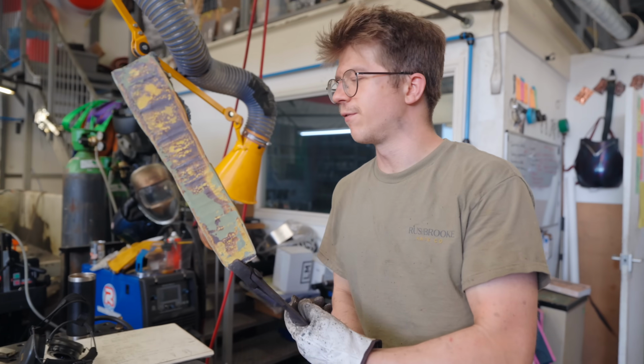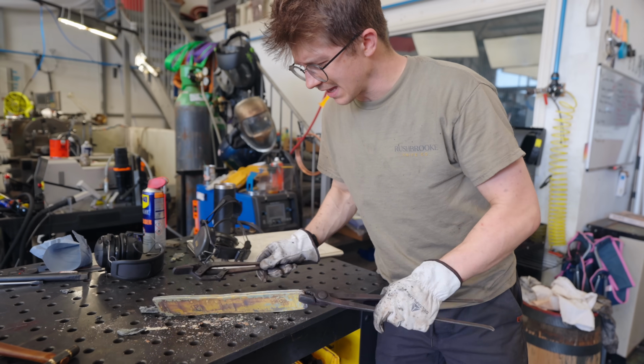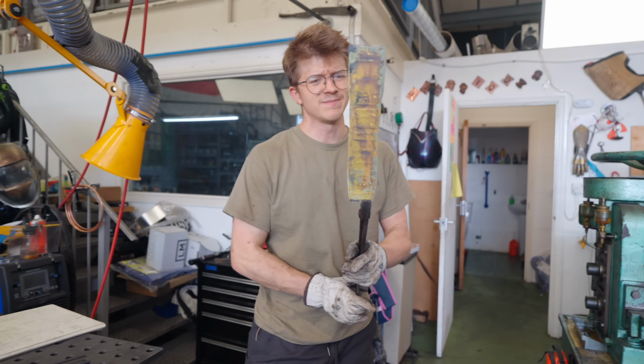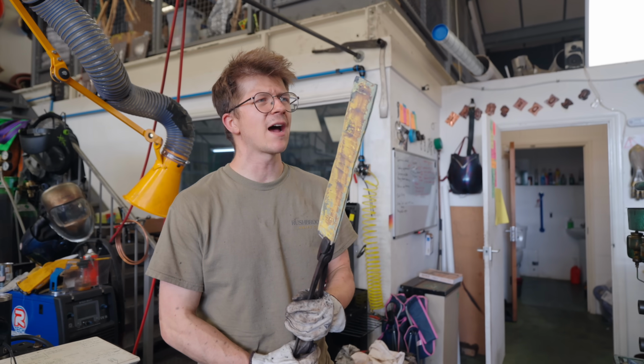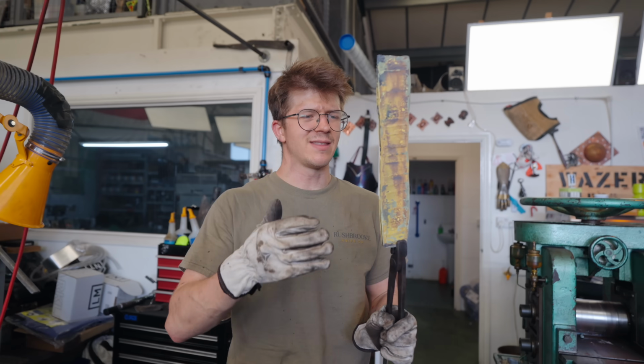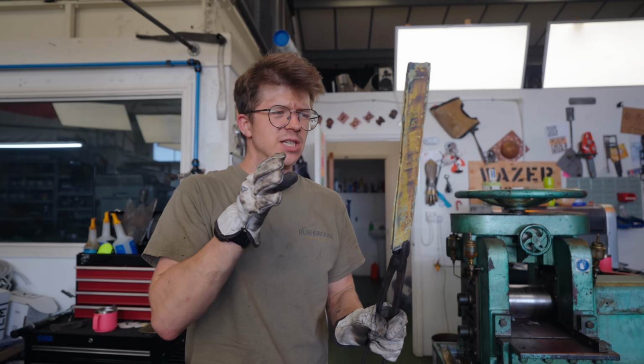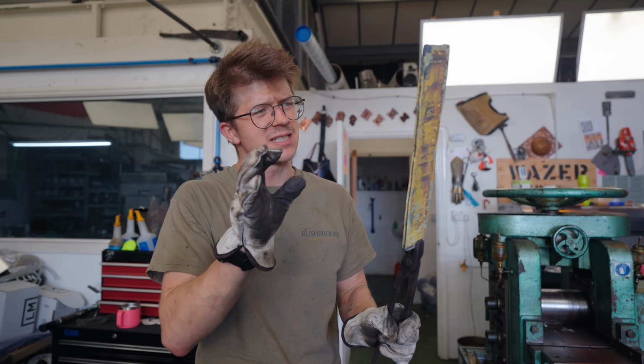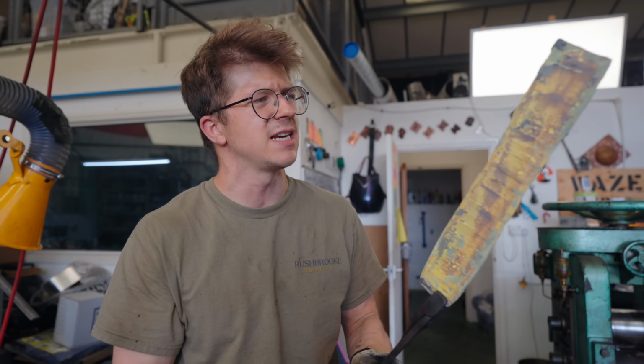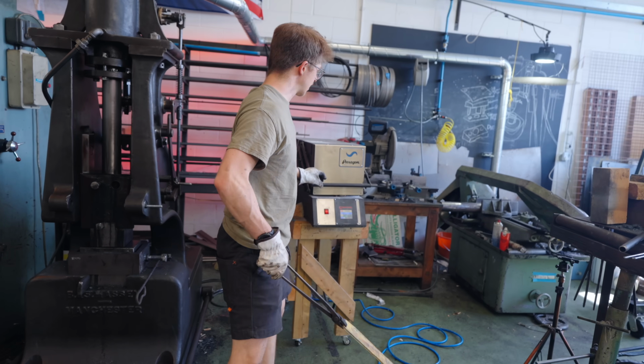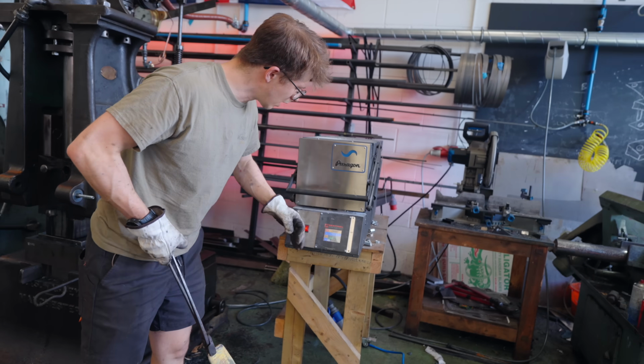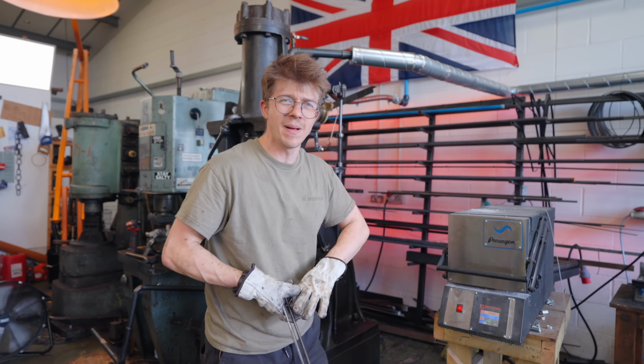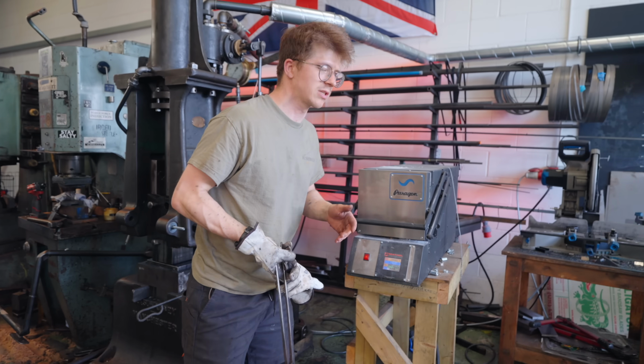That, unfortunately, my friends, is that intermetallic compound, which the only reason I can think for how that's happened is that the edge of the steel has kind of folded out past the interlayer, just on the edge, and touched the titanium, reacted with it, forming that intermetallic compound, and then, guess what? That intermetallic compound has a lower melting temperature than either steel or titanium.